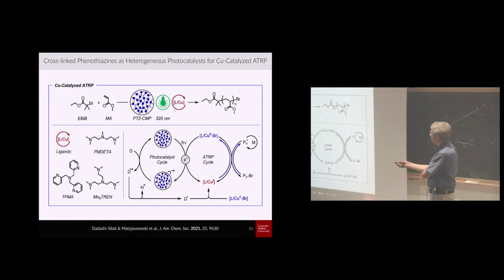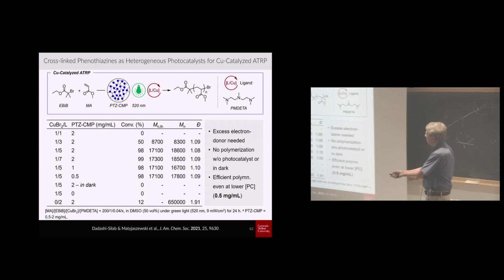So this is synthesis of polymethyl acrylate with this dual catalytic system, and you still have tolerance to oxygen as well. So if you look at the table with these results, the system with copper and ligand 1-to-1, so no excess of electron donor, you cannot reduce it back to the ground state, and there is no polymerization. If you have enough ligand, so excess of ligand, copper is a 1-to-1 complex in that case. If you have excess of ligand, which acts as electron donor, polymerization goes to 98, 99% conversion with very good control. If you have no light, of course, no polymerization.